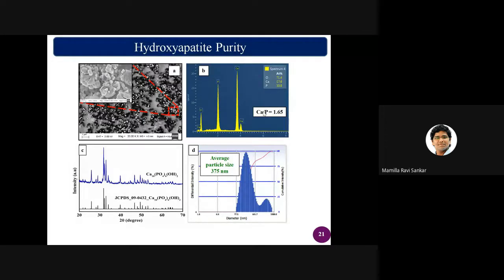Many people are well aware of developing the materials, but some people are not aware of how to check the purity of the material. So for example, you have multiple options. One rough option is EDS, energy dispersive spectroscopy, where you can check the composition levels. That will give you the calcium to phosphate ratio, which in the body is about 1.66 to 1.67, or sometimes in the range of 1.64 to 1.68. So that will give you a calcium to phosphate ratio of 1.65.